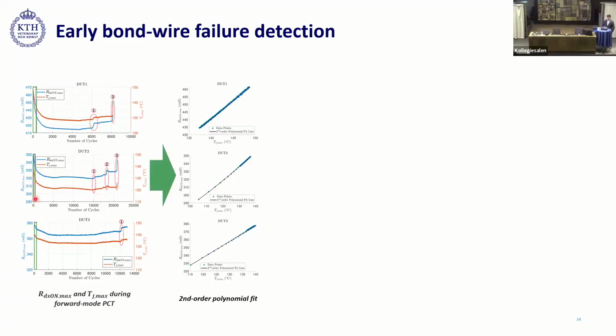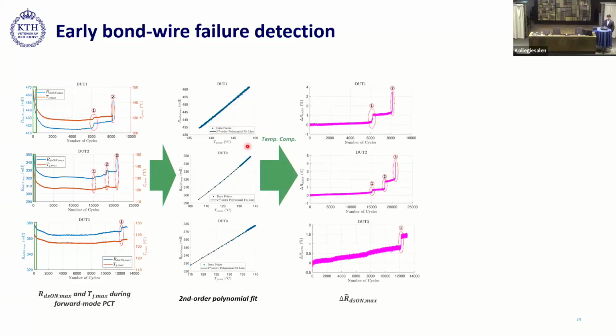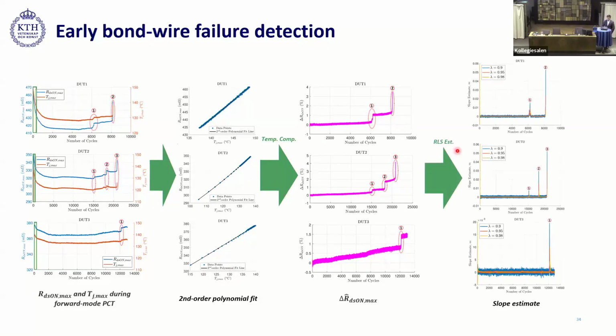So we took the data from the initial highlighted region to calculate the second order polynomial fit. And by using the second order polynomial fit and the RDS on max in the temperature compensation model, we get delta RDS on max, that is the temperature compensated signal. And here again, you can see that there is a drift, and then there's a jump. So this jump corresponds to bond wire liftoff, and the drift is because of threshold voltage. So when we feed this temperature compensated signal in the RLS estimator, we get the output like this. Here, the drift has been compensated, and we have peaks. So what we see here is that these peaks correspond to bond wire liftoff events. So these peaks can basically help us in detecting the bond wire liftoff events, at least during power cycling.